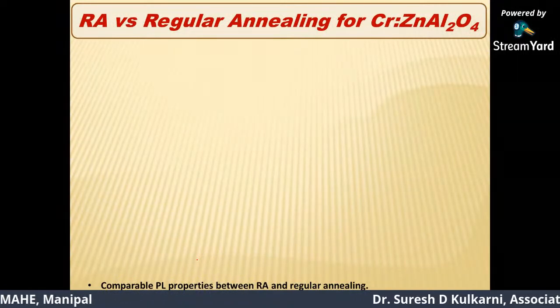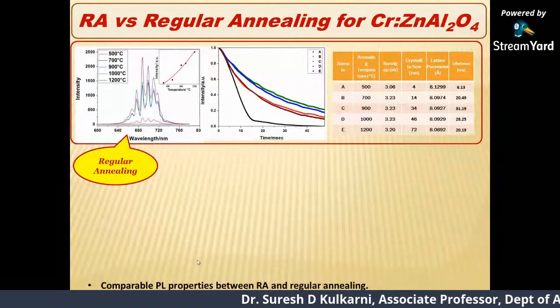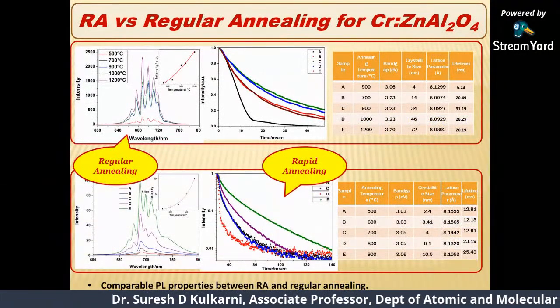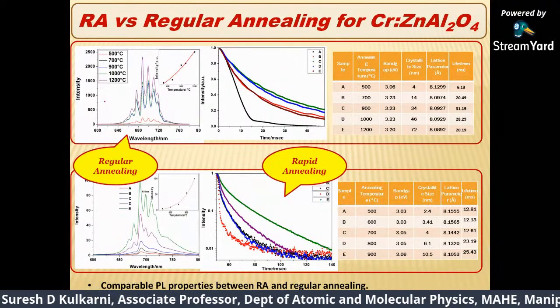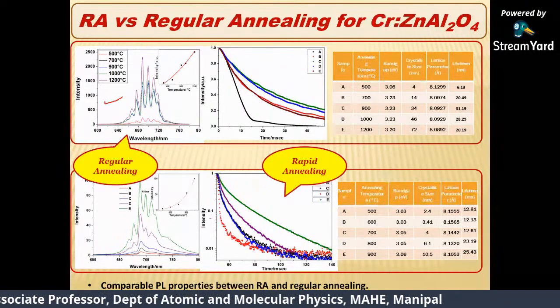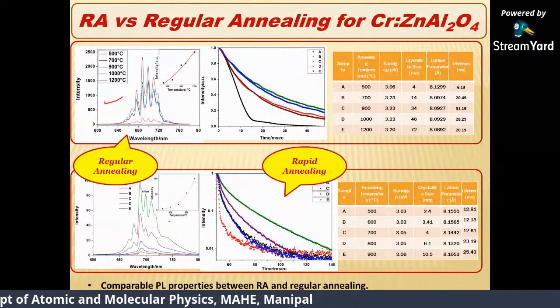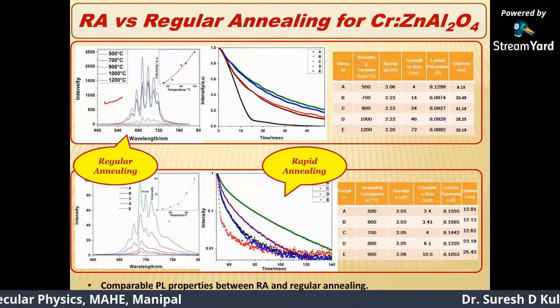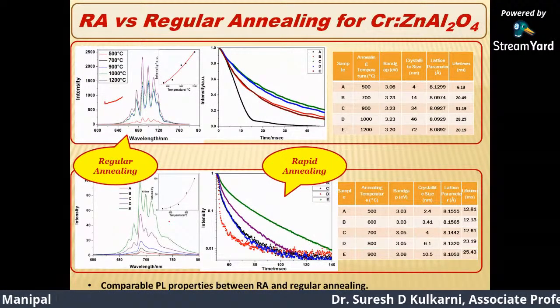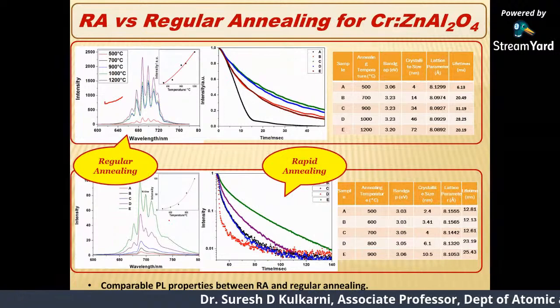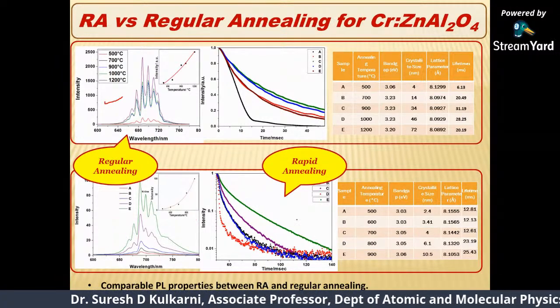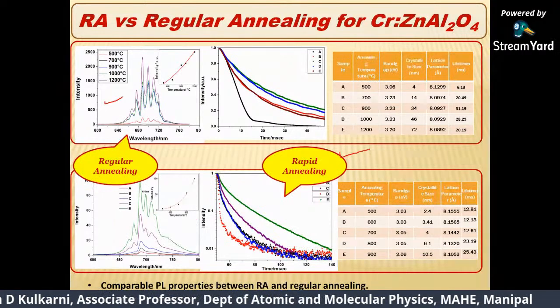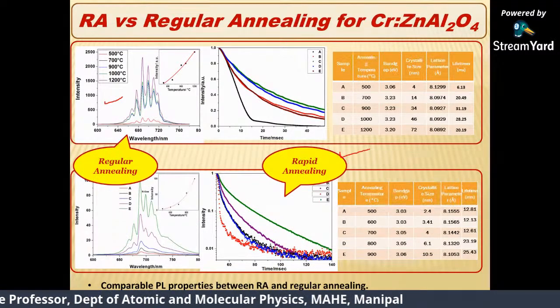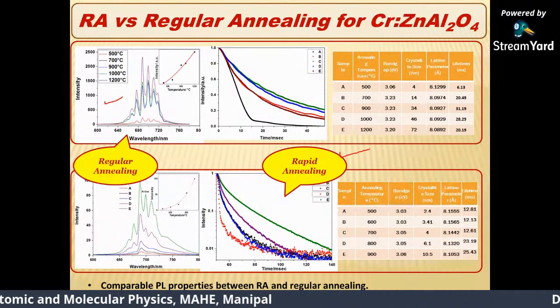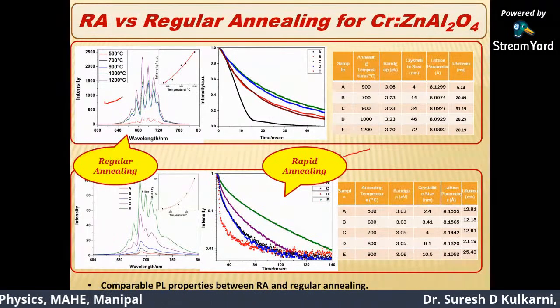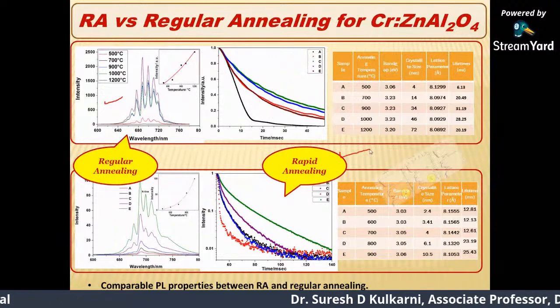And we did a comparison of the emission property. Okay, what we do for regular annealing is furnace annealing on the top and rapid annealing below. You can see the emission properties are comparable. We get good emission in a quick time of synthesis as well as processing. So the important thing to note here is that with the use of rapid annealing, I have done two parts: one is the synthesis and the other is the annealing, in a single go. So that is an important achievement of this system that we have developed.